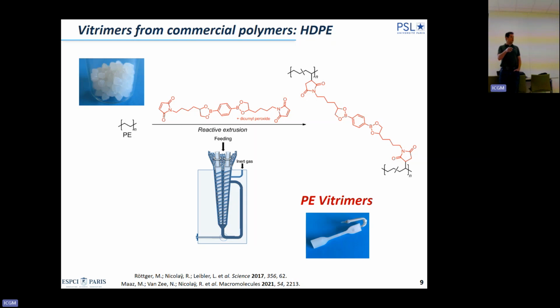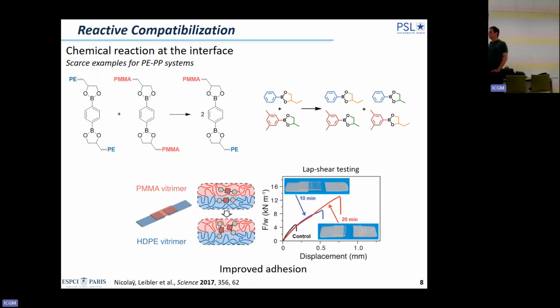So with Ludwik, we showed that we can transform PE by reactive processing, for example, using a bis-maleimide with a bis-dioxaborolane in the center, using radical cross-linking, radical grafting with a dicumyl peroxide. Through reactive extrusion, we can go toward a material which we call a vitrimer, which is a chemically cross-linked material, which is still processable. So my message here is that we can get to these objects through reactive processing.